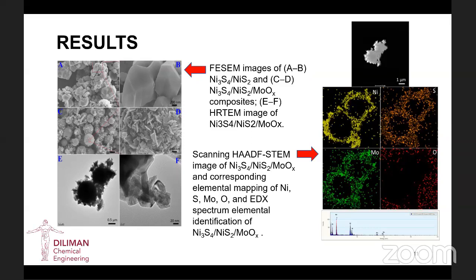3 micrometers, whereas the images in C and D show comparably homogeneous microspheres with size ranging from 2 to 4.5 micrometers, with some nanosheets intertwined on the surface of the microspheres. So the thickness of these nanosheets ranges from 20 to 40 nanometers and from 150 to 300 nanometers respectively.